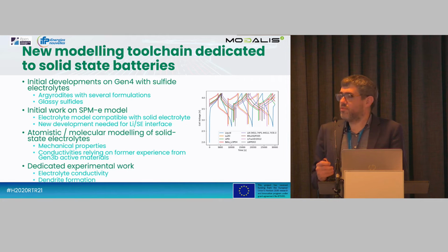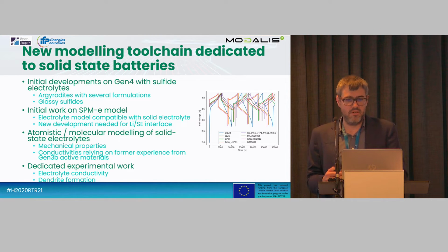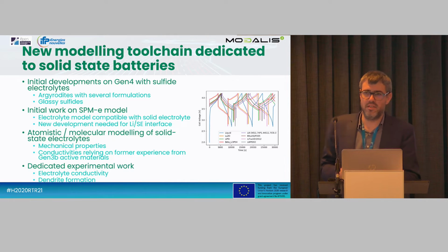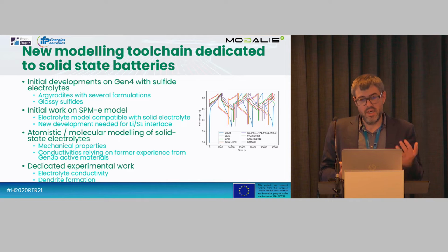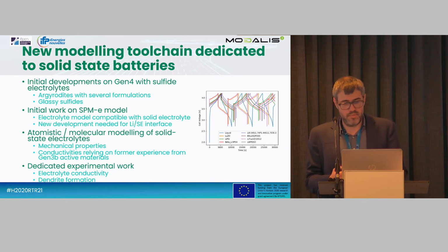Now that this has been developed for Generation 3, the work has also begun on Generation 4 in order to understand the behavior of electrolytes. So the main subject of study that we are using in this is sulfide electrolytes, especially argyrodites, with several formulations. So this will aim at comparing the result from one formulation to the other, thanks to atomistic modeling, and then predict the new behavior when you change the formulation. And then we'll go to glassy sulfide, which is a new challenge, especially for atomistic calculations, which are much more complex. At the same time, we have adapted the SPMe model for solid-state electrolytes.